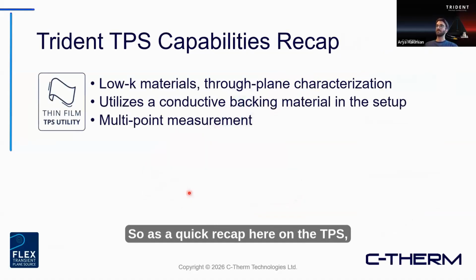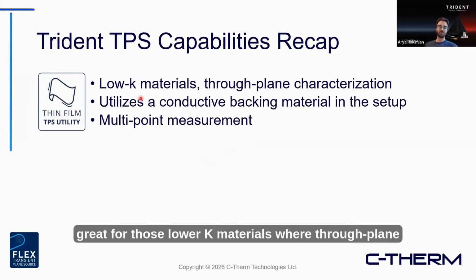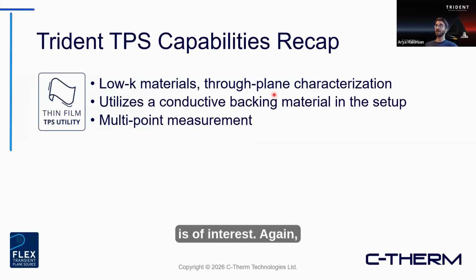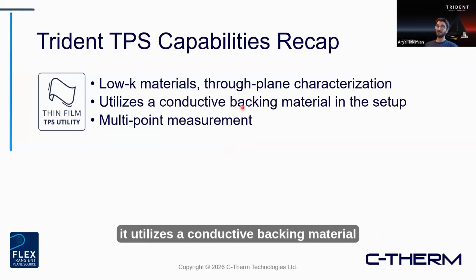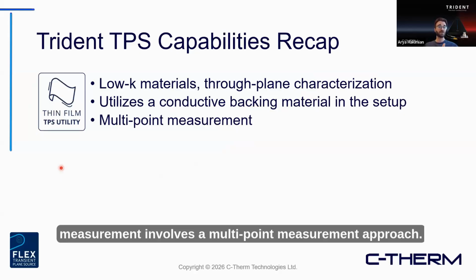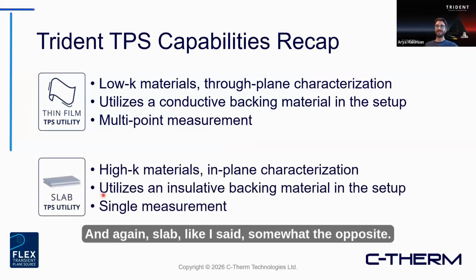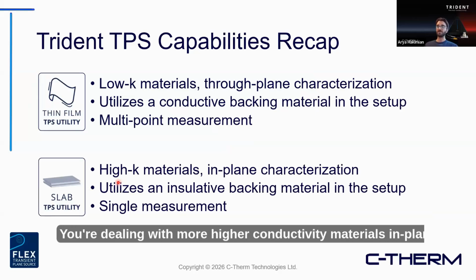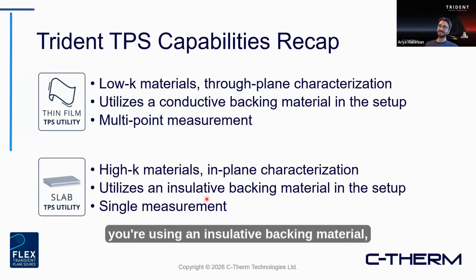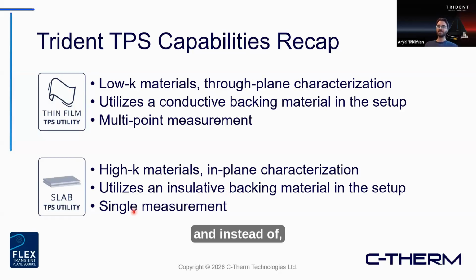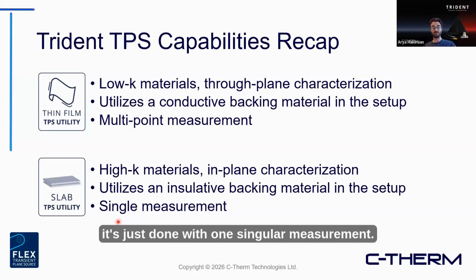So as a quick recap here on the TPS, the thin films utility is going to be really great for those lower K materials where through plane is of interest. Again, it utilizes a conductive backing material, and the overall flow of your measurement involves a multi-point measurement approach. And slab, like I said, is somewhat the opposite. You're dealing with higher conductivity materials in plane. You're using an insulative backing material, and it's done with just one singular measurement.